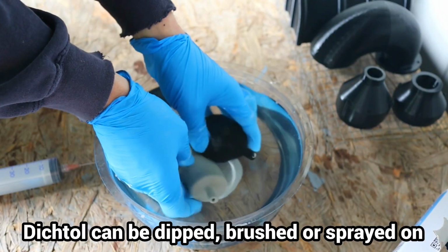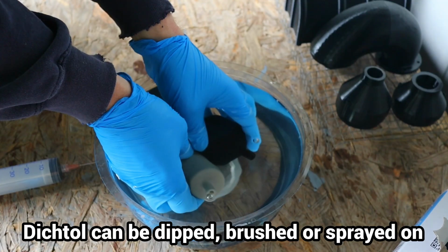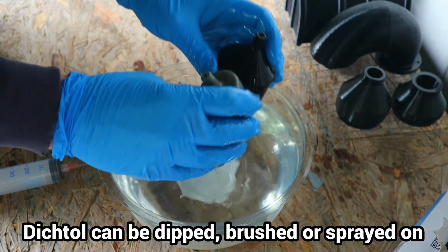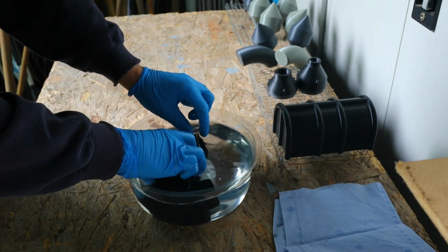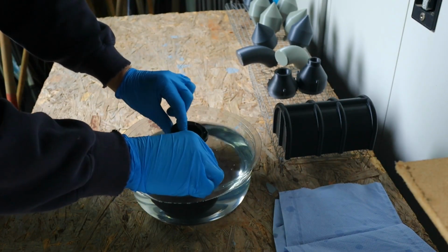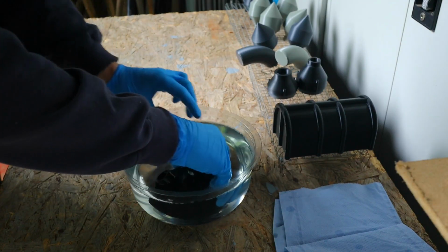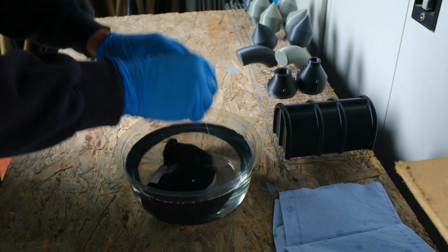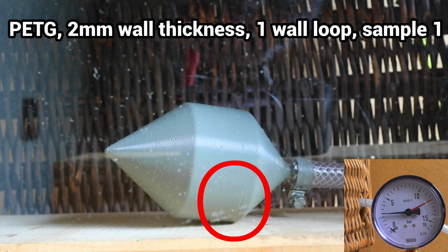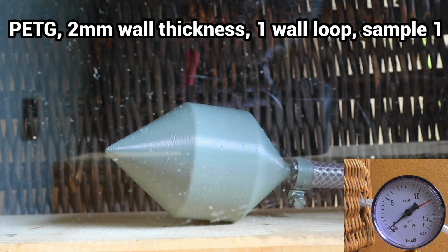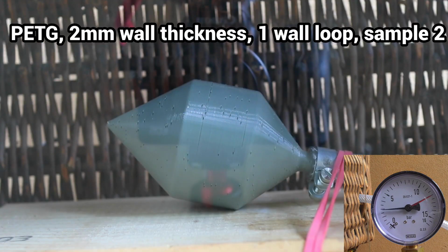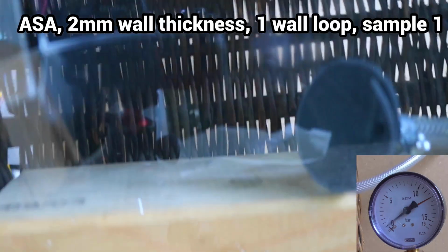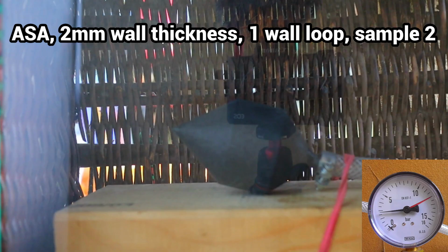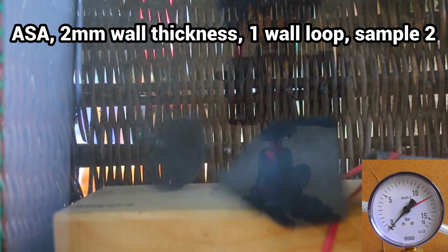My design of the first batch of pressure test pieces was rather impractical. The small inlet opening made it difficult to fill them with enough Dichtol. Dichtol AM contains solvents. If you don't like the smell, it is better to use the water-based Dichtol AM Hydro instead. With the test samples made of PETG with a wall thickness of 2 mm and only one wall loop, the layers tear open at 3 bar pressure. The ASA parts with thin wall thicknesses and a single wall layer exploded spectacularly at 4 bar.